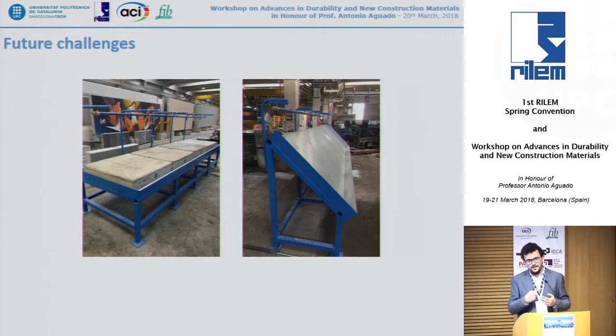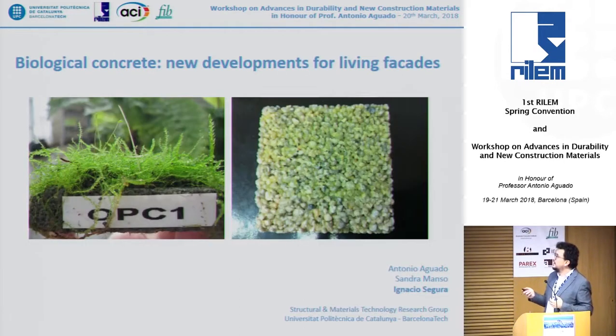We also have a very interesting challenge, which is how we can use superplasticizers that are normally used for Portland cement with this new magnesium phosphate concrete, because there are several problems with the dosage and the workability, and we cannot increase the use of water in order to have good workability in our material.